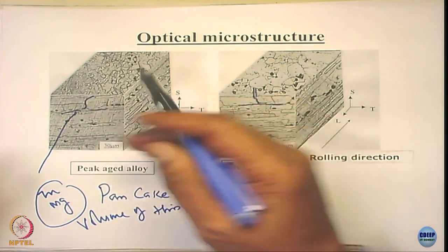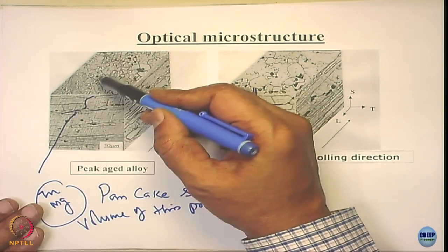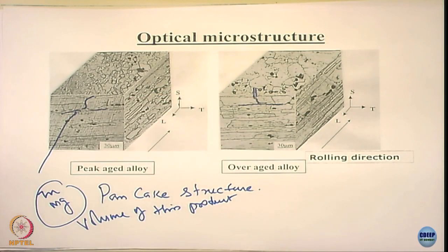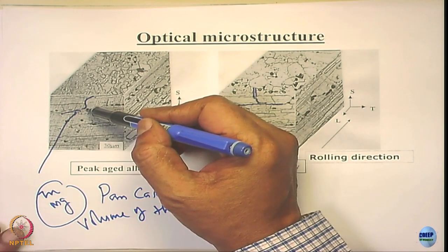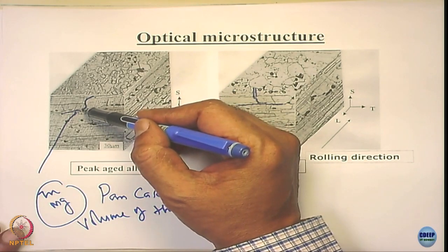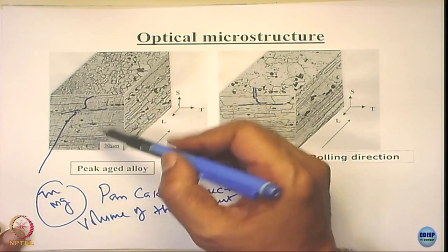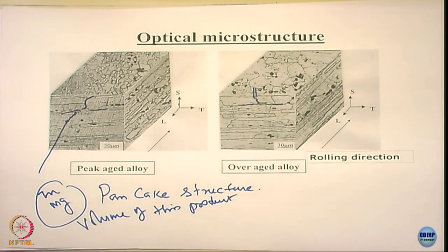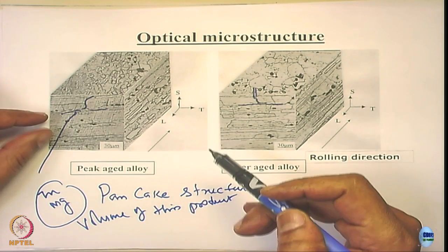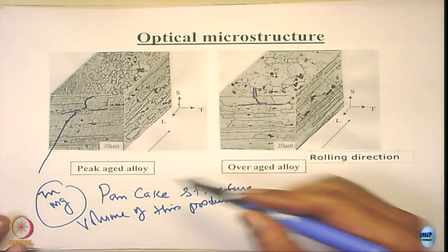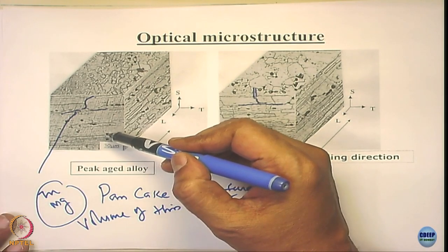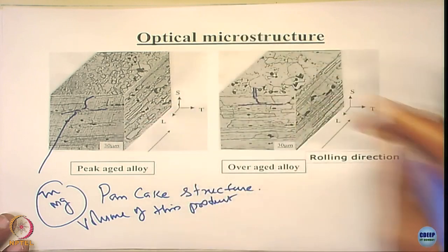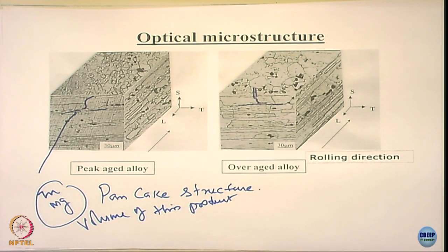It is going to strain, it is going to lift up. That means the grain starts opening. There are going to be internal stresses. In addition to corrosion happening because of preferential dissolution of the grain boundary precipitates, it is also going to exert certain stresses, and so there is going to be delamination along the grain boundaries. The grains start lifting from the material below the subsurface. So it exfoliates, they delaminate actually. So that is what really happens in the case of these materials.